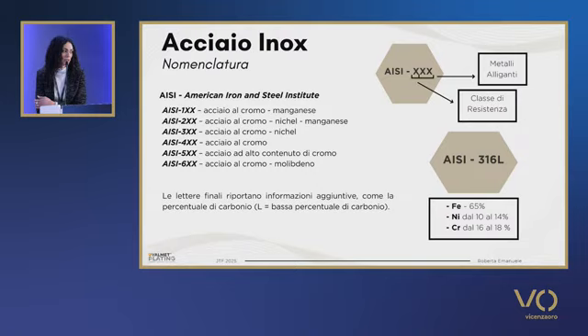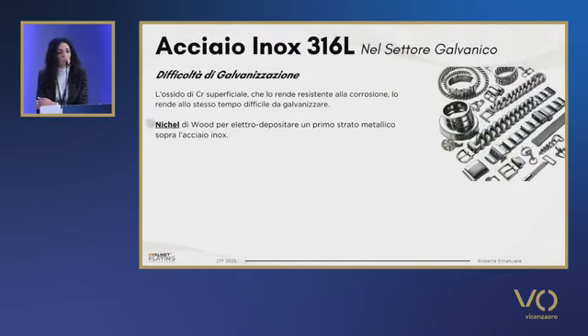AISI 316L is a specific type of stainless steel. It is a chromium nickel alloy containing 65% of iron, chromium ranging between 16 and 18, and nickel from 10 to 14%. This type of steel is also used for medical purposes. It is not widely coated because, again, the coating is very difficult in the case of this type of steel. The chromium oxide layer makes it resistant to corrosion, so much so that coating is very difficult.